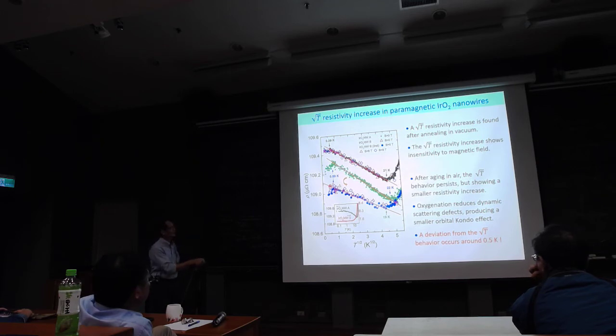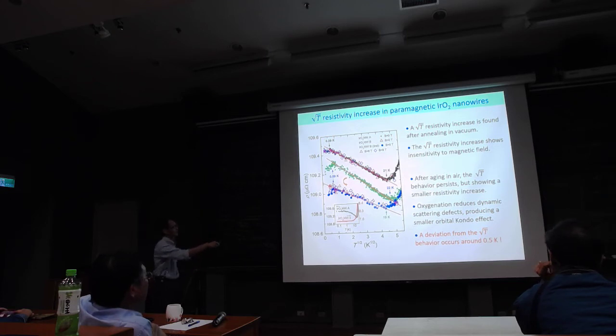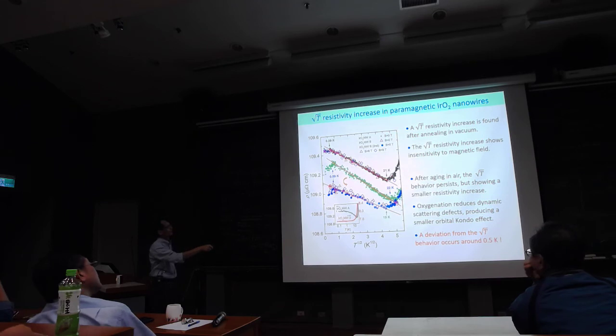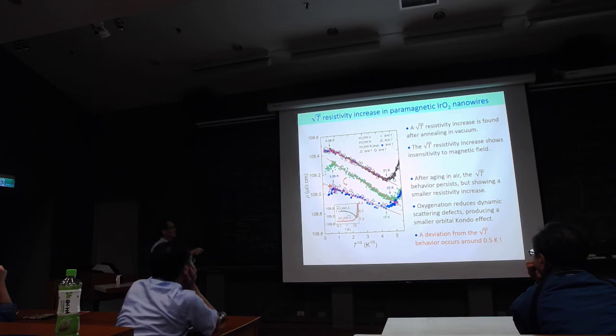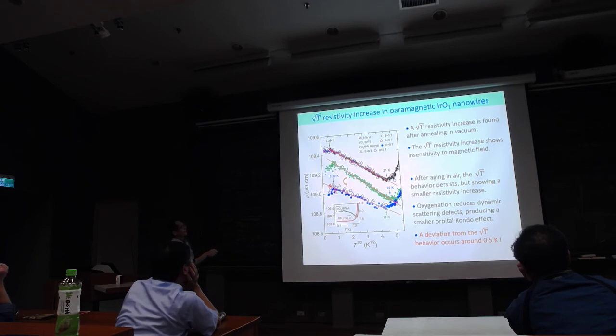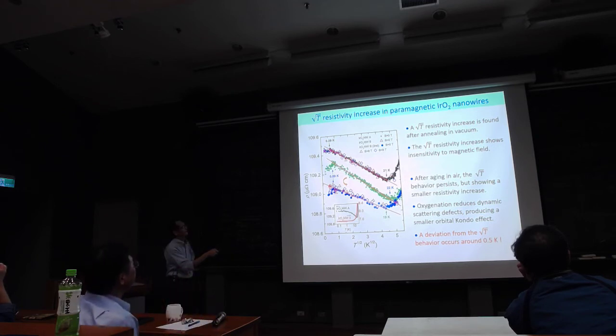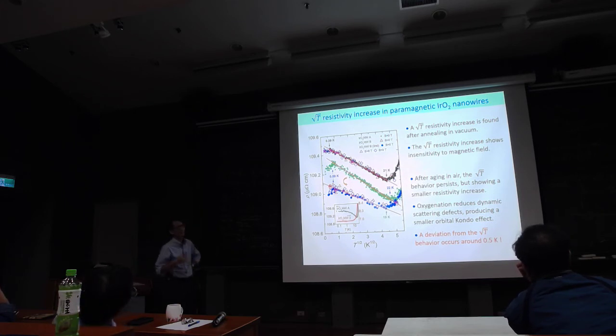So at higher temperature, above 20 or 30 Kelvin, here's the standard Boltzmann transport. But at low temperatures, resistivity increases, but the scale is actually very small. But we have a resistivity increase, square root T. And then in zero magnetic field, and in 6 tesla, 9 tesla. So you can measure in zero field and apply magnetic field.